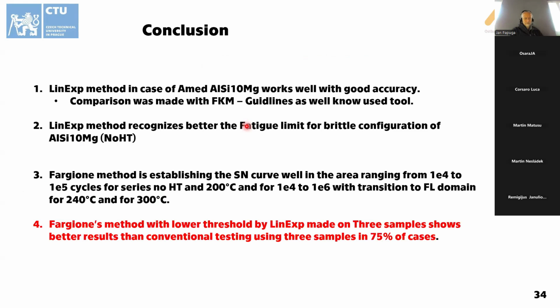So to conclude this presentation, the LinExp method, in the case of additively manufactured aluminum alloy, or this powder exactly, works well with a good accuracy, I would say, for nearly all of the series presented in this work. But we are trying to extend this knowledge as much as possible these days. The comparison was the FKM guideline. It's hard to compare it directly, but for the non-heat treated variant, it works better than the FKM guideline, which is only a plus point, although in some cases it works better as well. The LinExp method can recognize better the fatigue limit for the non-heat treated variant.